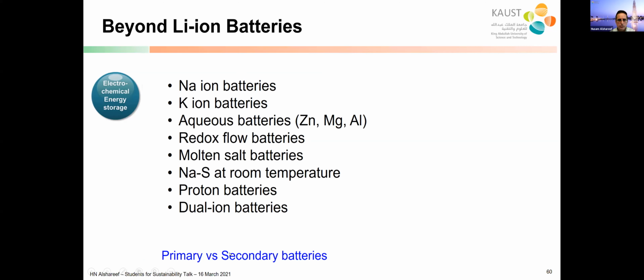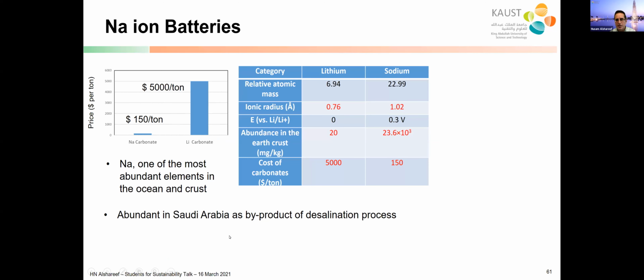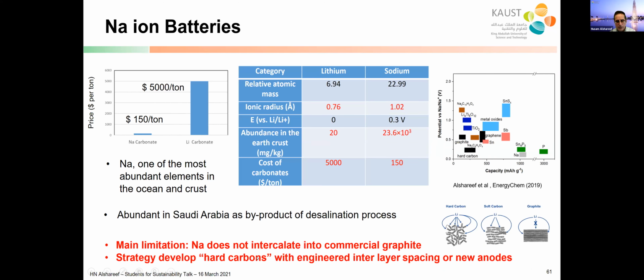So what are they looking into? For example, sodium-ion batteries. This is the price of a ton of sodium carbonate and the price of a ton of lithium carbonate. You go from $150 to $5,000. So this huge price difference, obviously, is big. And Saudi Arabia, since we're in Saudi Arabia, has a lot of sodium as a byproduct of desalination. The problem with sodium, however, is that the ion is bigger than that of lithium. Therefore, graphite, which has been the commercialized anode for lithium-ion batteries, does not work for sodium.